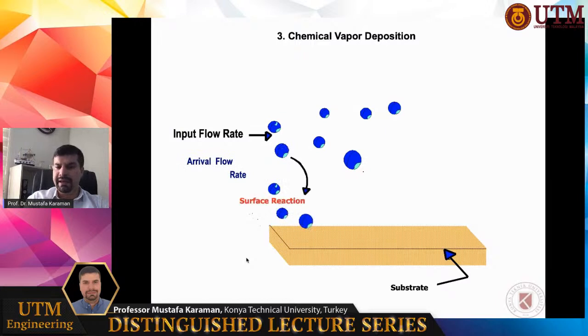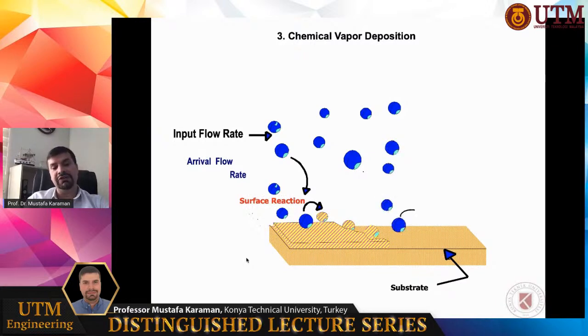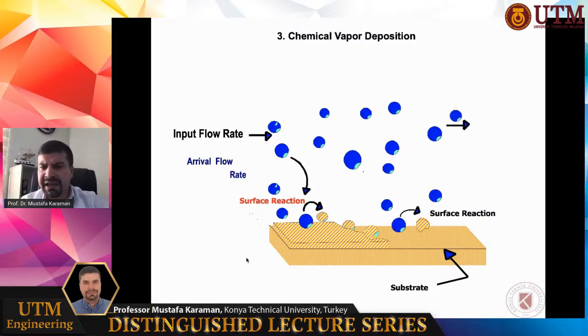The input gases are forced to enter the reactor where the substrate is placed, and the precursor vapors are diffused from the bulk gas to the surface, through the surface, with different kinds of mass transfer mechanisms. Once the vapors arrive at the surface, they are usually adsorbed at the surface, physically or chemically, depending on the surface temperature. And in the end, after the chemical reactions at the surface, dense uniform films are obtained.